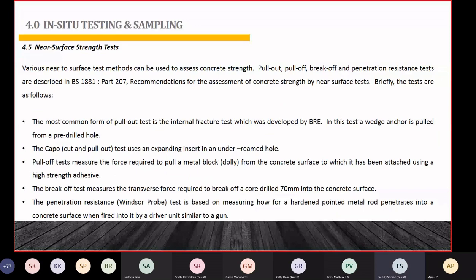Now, near surface strength test. As I mentioned before, this is to find out the pull-out and pull-off test actually. In Europe, there's a practice when they construct a large building and important structures, they will put some insert in it. Later, at some point of time in the future, if there is some strength issue, they can pull out that insert and find out the strength of the concrete. There are some methods to interpret the strength of the concrete. That's very useful. In Europe it is widely used.